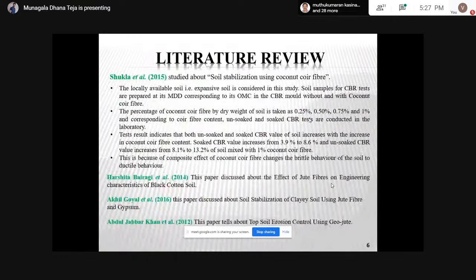Shukla et al. also did soil stabilization using coconut coir fiber. He took local expansive soils and used different percentages by dry weight of soil. He did unsoaked and soaked CBR tests and also got better results with inclusion of coconut coir fiber. The soaked CBR value increases from 3.9 to 8.6 and unsoaked from 8.1 to 13.2 with 1% coconut coir fiber, which is the optimum. He concluded that increasing coconut fiber increases the strength, because the composite effect of coconut fiber changes the brittle behavior of the soil to ductile behavior. And some other three literatures I saw: Harshita Bairagi, Akhil Goyal and Abdul Jabbar Khan.